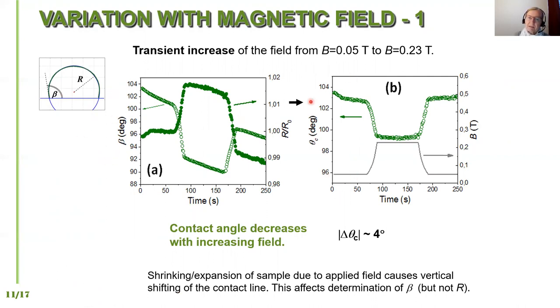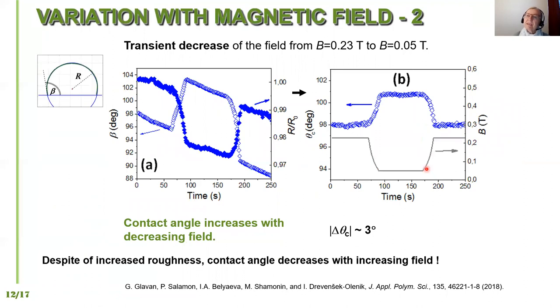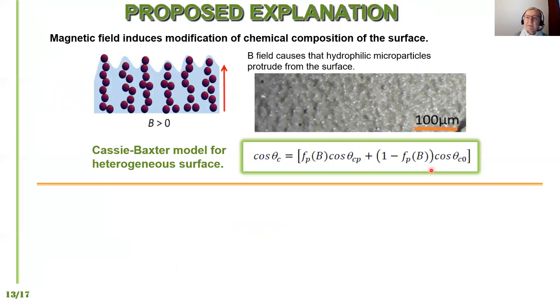We came to a surprising observation. In the first experiment, we deposited a droplet on the surface at low magnetic field, increased the field, then decreased it again, and observed that the contact angle was larger at lower magnetic field. We also made the opposite experiment: placing a droplet on the surface when it was already exposed to a magnetic field, then removing and reapplying the field. The contact angle actually decreases at higher magnetic field — the opposite of what one would expect.